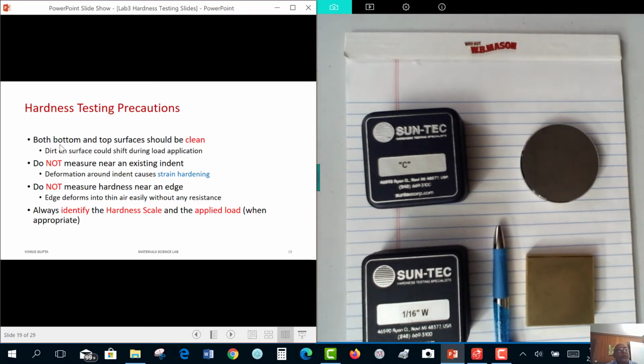Before I go on, in any case, whatever you do, you want to make sure that both the bottom and top surfaces are clean because the dirt on the surface could shift. Now, you have been asking about questions on my quizzes. Obviously, when you apply a certain load, whether it is 3000 kgs or in our case, 150 kgs in C scale that we are going to apply today, the indentation size does not change. So in Brinell, since we measured the indentation size, our hardness number would not change even if the specimen was dirty or there were some tiny particles acting as springs at the bottom. But in Rockwell hardness, it is the machine that measures the depth of indentation. So the machine thinks it has gone deeper into the material than it has, and therefore to the machine it appears that the material is softer than it is.